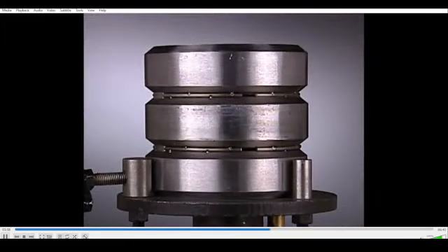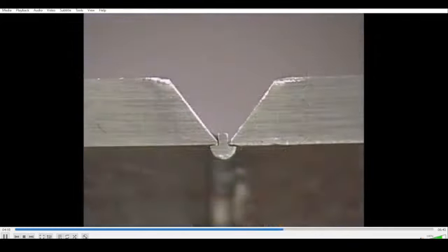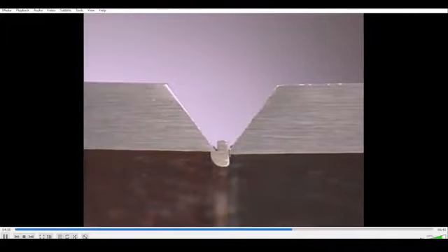Consumable inserts are used to assure complete uniform joint penetration and root reinforcement. They are also used in confined areas where welding with a filler wire might be difficult. There are several types of consumable inserts. One of the most common is the A or EB type, which forms a ledge for both edges of the joint. The J insert is similar to the A, except that one side is flat and can allow for a certain amount of joint misalignment.